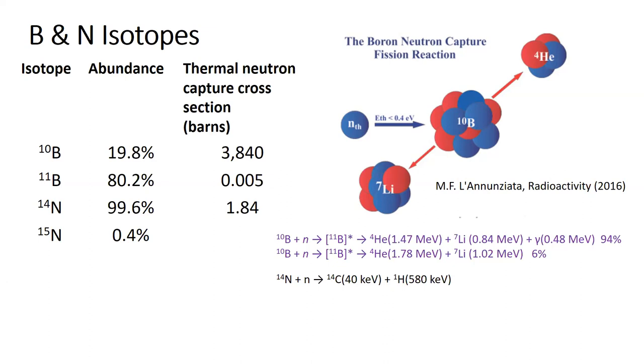The most notable thing about boron 10 is that it has strong interactions with neutrons. You see the thermal neutron capture cross section is almost 4,000, and that compares with most elements having a cross section of about one barn or less. So boron 10 will react with a neutron in a nuclear reaction to form lithium and alpha particles, whereas boron 11 is pretty much transparent to neutrons. And nitrogen has just a little bit of neutron activity. So key things to notice is boron comes in two isotopes, and when I talk about monoisotopic, I mean either one boron isotope or the other, boron 10 or 11.